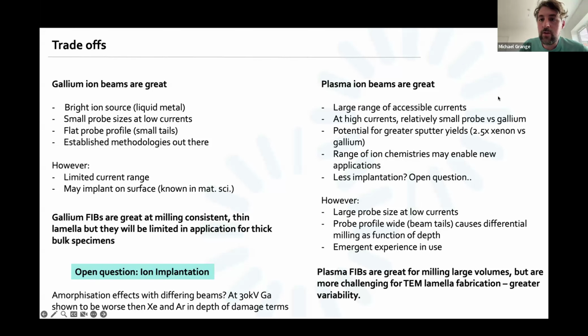And on the flip side, plasma ion beams are great. They have a large range of accessible currents, but they do have large probe sizes compared to gallium at the same current. And so if you want to get really thin lamella, you might have to work a bit harder or do something a bit more exotic. And I think the automation for plasma is getting much better. In-house we are doing regularly automated lamella production, but there's a much greater experience with gallium.